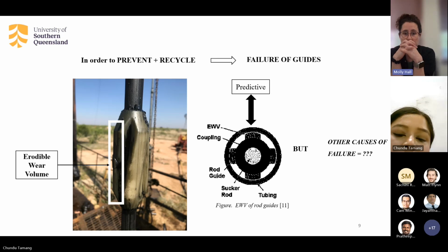And the existing literature studies on rod guides are solely focused on the concept of erodible wear volume only in order to increase its service life. However, still in current practice, what is happening is the operators replace the rod guides just based off prediction that it has lost a significant amount of its erodible wear volume without actual site inspection. So if we want to produce a proper recycling technology, it is very important to determine the other causes of failure so that we can evaluate its recyclability.